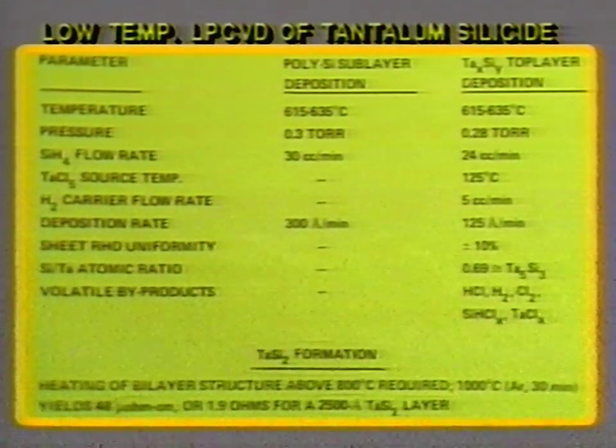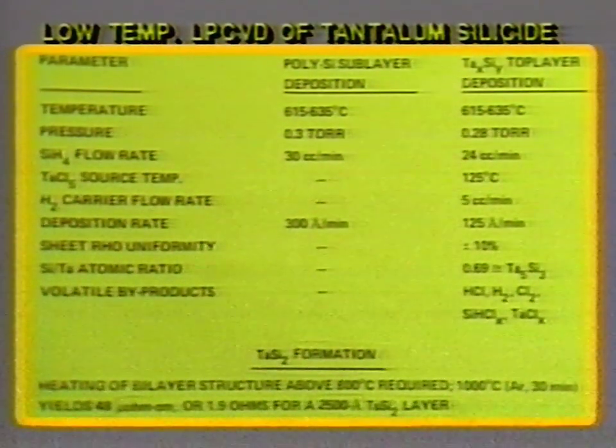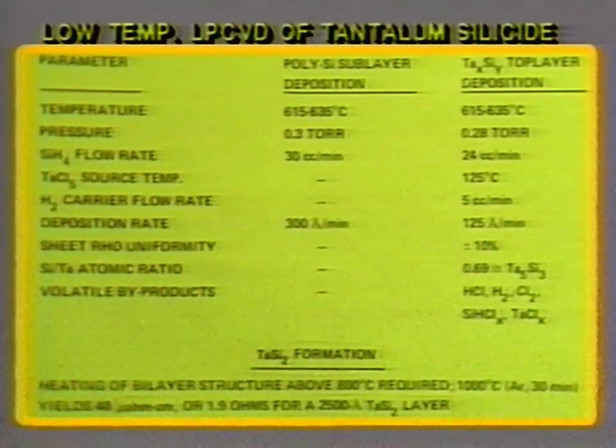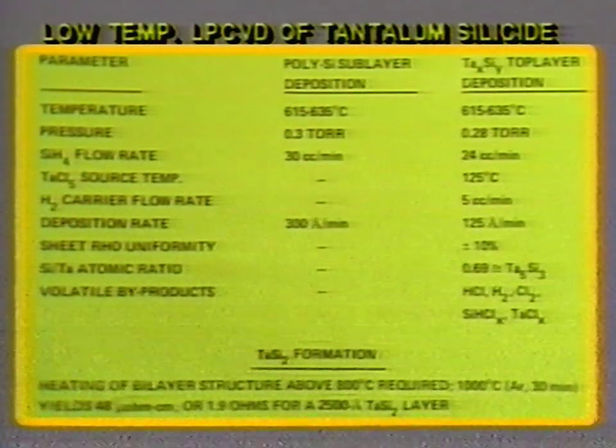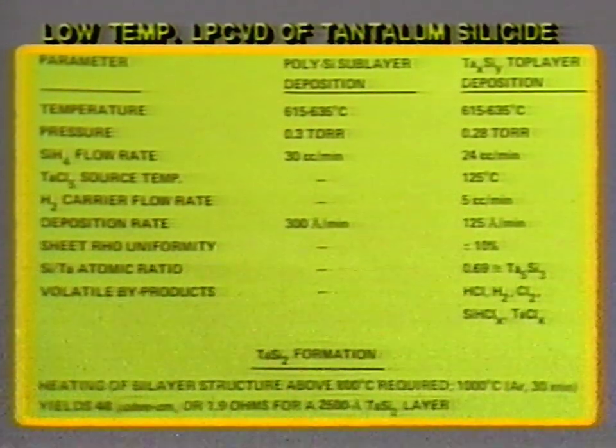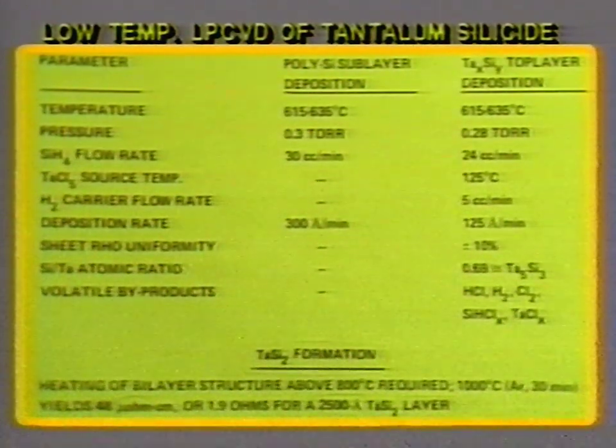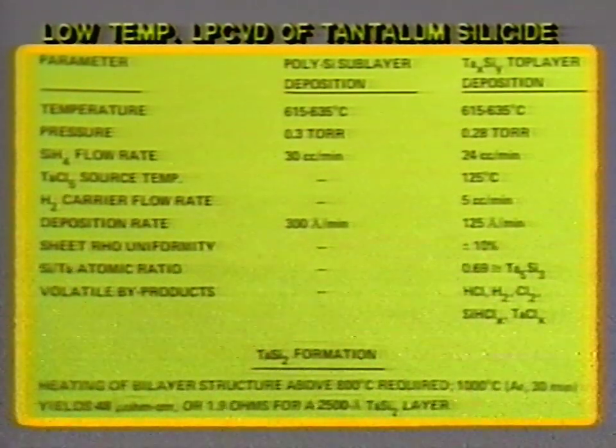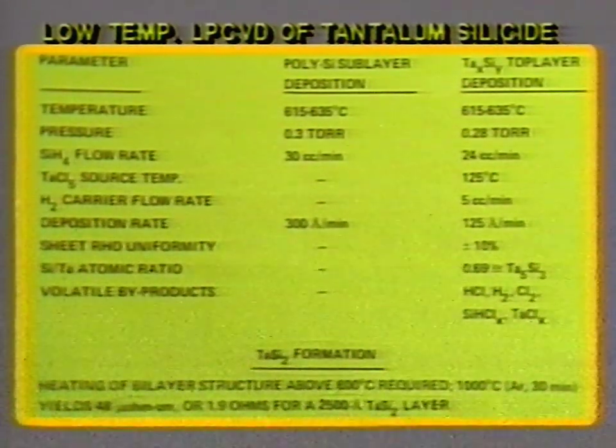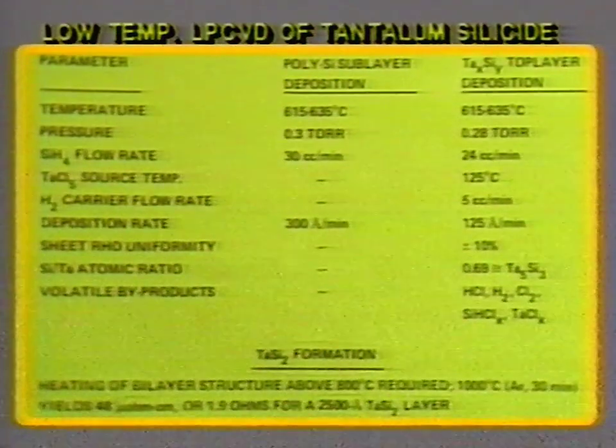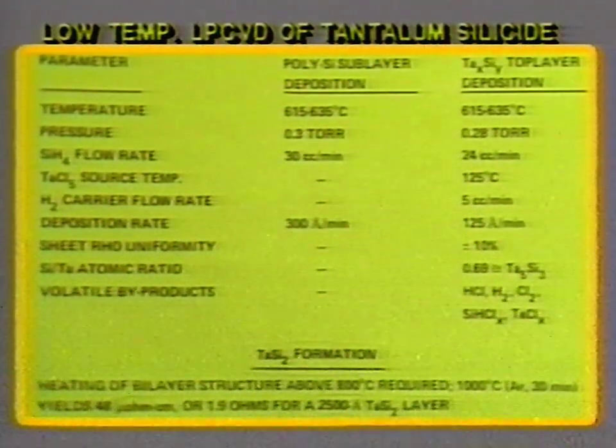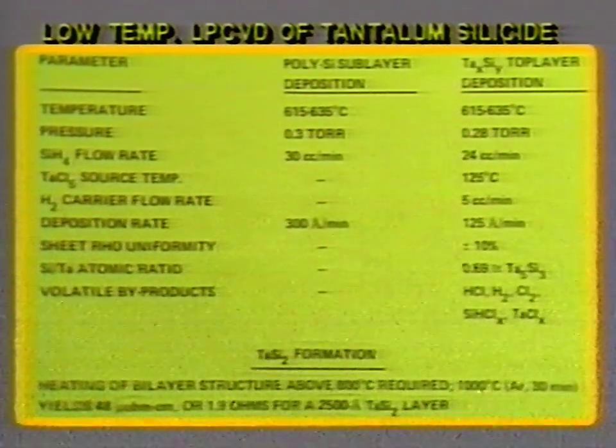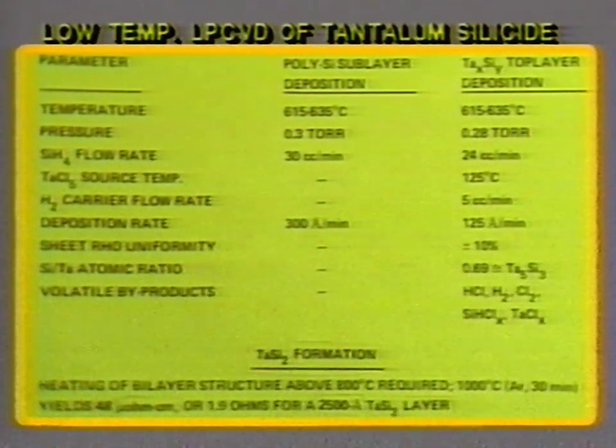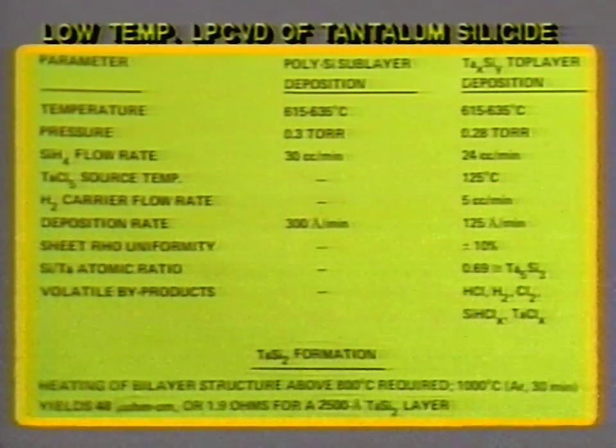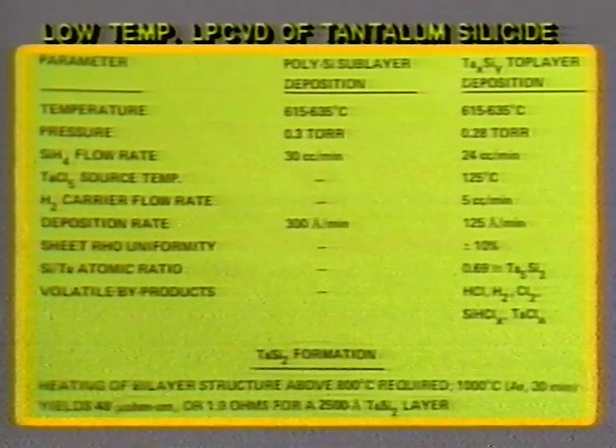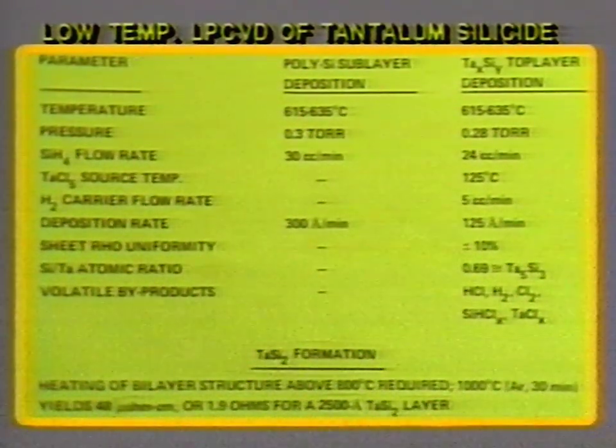Once we have obtained a film of polysilicon sufficiently thick, we now switch over to the tantalum doping here. In this case, we use tantalum pentachloride as the source material, which is kept at a temperature of 125 degrees C to obtain sufficient vapor pressure to get the reaction going. We also use hydrogen as the carrier gas for introducing the vapor into the reactor. In this case, the deposition rate is about 125 angstroms per minute. And what we wind up with is a composition of tantalum silicide, as shown here, which is not what we really want.